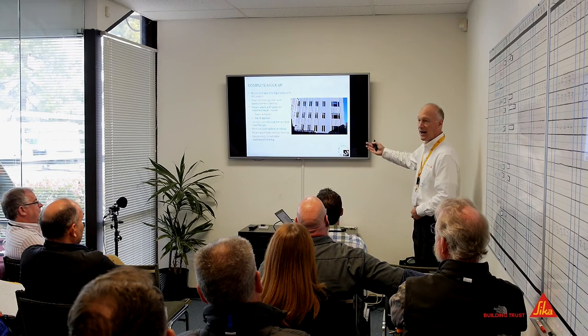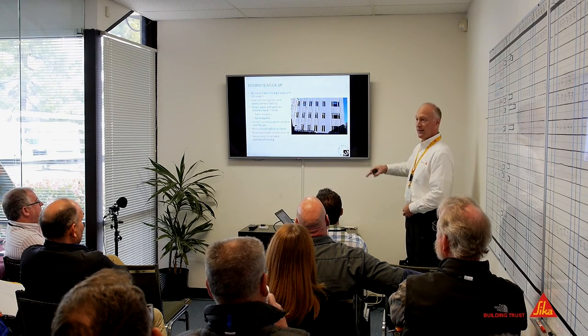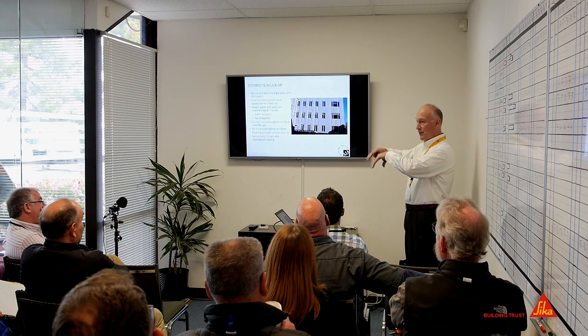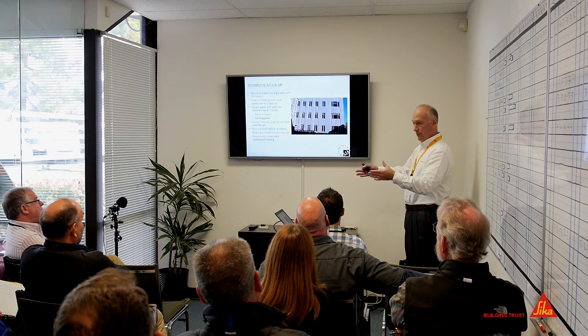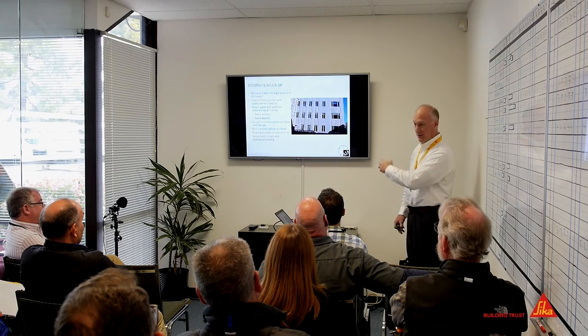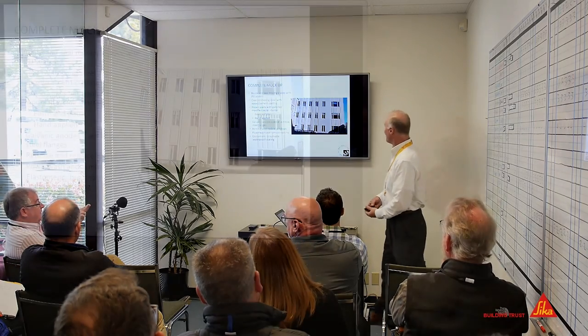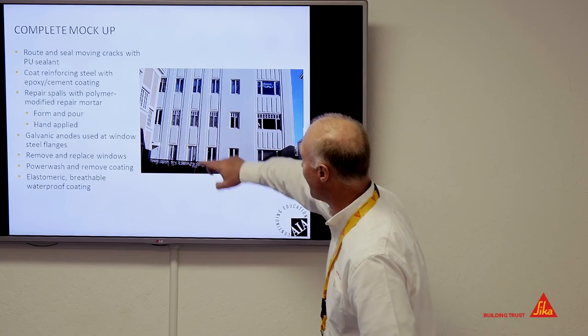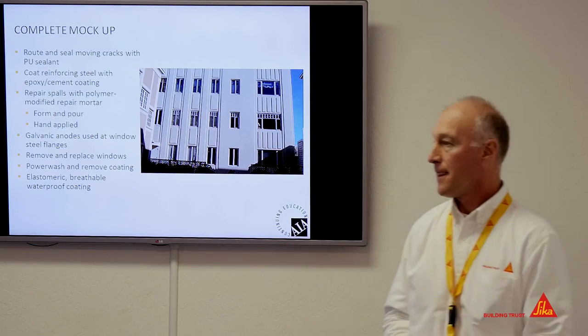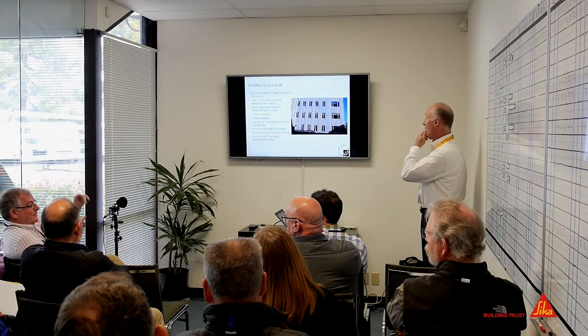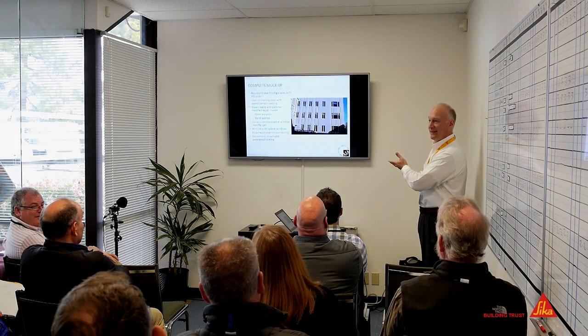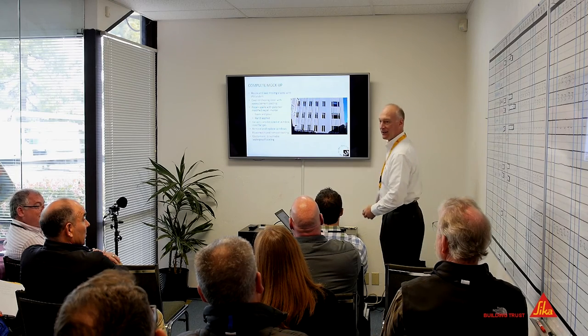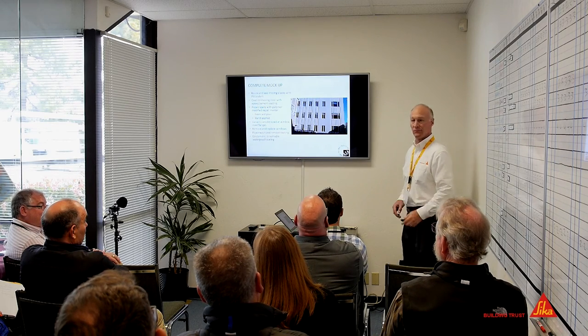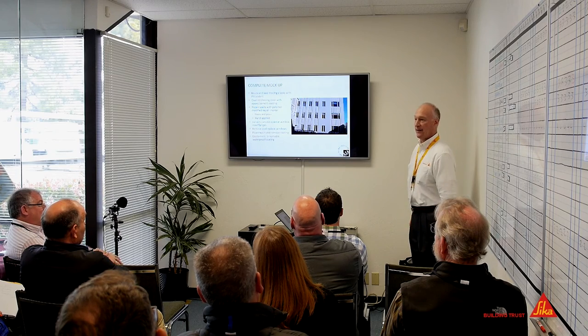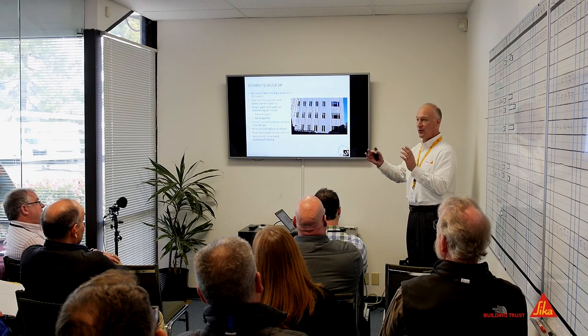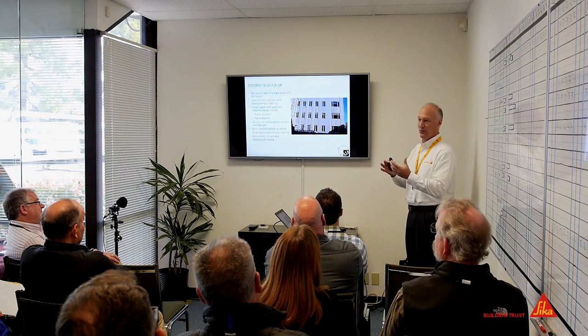I picked up on that, and that's why I highlighted it as part of the scope of this job. For whatever reason, the consultant wanted to do several floors and get a good square footage area. But you're right, that's a much larger mock-up than normal. Usually a mock-up might have been just this area here. It is a big building, though, and if you stand back and you want to see the full impact of the change, it's 5%. Actually quite helpful. I would guess that it also represents a better representation of all the different challenges that they're going to face. Mm-hmm. And that's what they're after. So the size should really try to capture as many of the details that you're after.